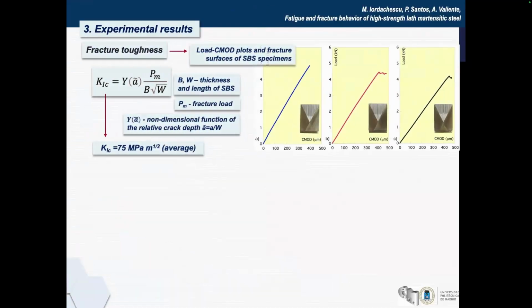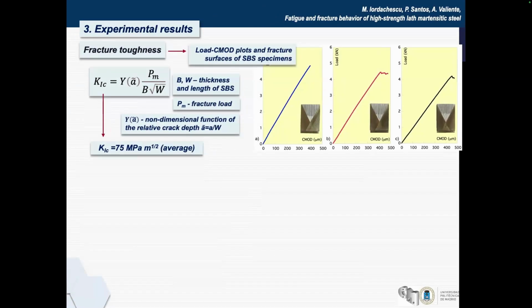Now, related to fracture toughness, according to the standard, we used these equations. According to the data that is plotted here, the load during testing and also load versus crack mouth opening displacement. Here we also have the images of the broken specimen. The maximum load in this case was used in the equation, and from these 3 tests, an average of 75 megapascal square root of meter was obtained as fracture toughness.